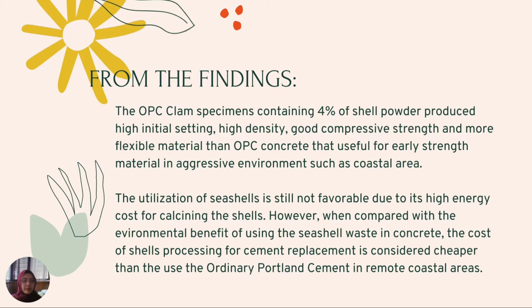From the findings, we could see that the OPC clam specimen containing 4% of shell powder produced high initial setting, high density, good compressive strength, and more flexible material than OPC concrete that useful for early strength material in aggressive environments such as coastal area. The utilization of seashell is still not favorable due to its high energy cost for calcining the shells. However, when compared with the environmental benefit of using the seashell waste in concrete, the cost of shells processing for cement replacement is considered cheaper than the use of the ordinary Portland cement in remote coastal areas.